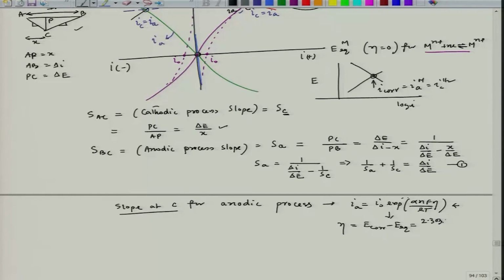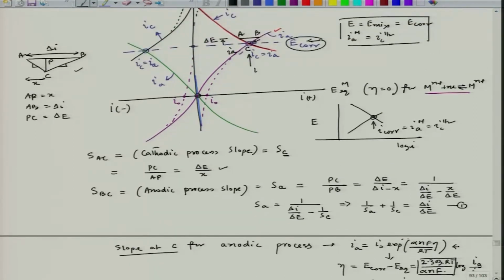2.303 RT by alpha NF log of IA by I0, and this quantity is nothing but beta A, times log of IA by I0, and IA I can replace as I corr, since at this location, IA equal to I corr equal to IC. This is hydrogen, this is metal, so this is metal.